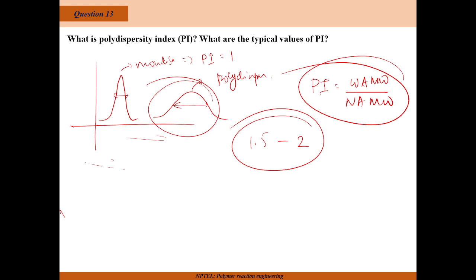With free radical initiated polymers, I am initiating all the monomers together, but some will proceed first because of the availability of monomer. Some will go fast, some will go less. Generally, when we put that in a GPC, we will see this broad distribution for the free radical initiated polymers. Anionic or cationic are specific polymerizations where we can go close to one, but definitely it will not be one. Getting a narrow chain distribution in any polymer is really tough, but still we can take it close to one.